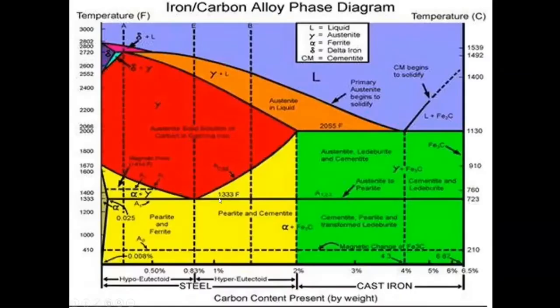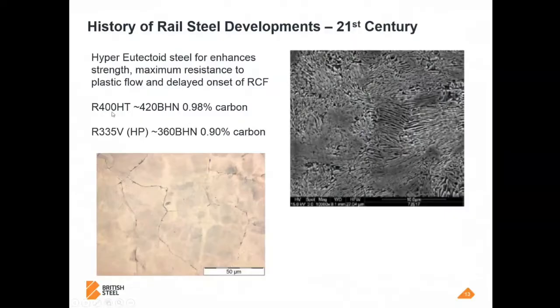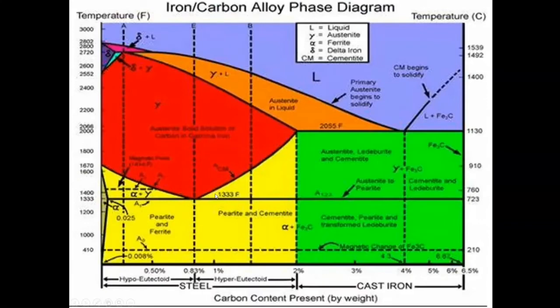The problem with hyper-eutectoid rail steels is that as it's cooling down and it transforms, you often pass through this little triangle here and you form continuous networks of grain boundary cementite, which is deleterious to the performance. It acts as a fracture path and it makes fatigue cracks, or any cracks, flow very quickly through it. It lowers the toughness and it's undesirable. So the way that voestalpine get around that with their R400HT grade is they accelerate cool it aggressively through this little triangle here, so it spends the minimum amount of time in it and it forms only very thin and broken and diffuse